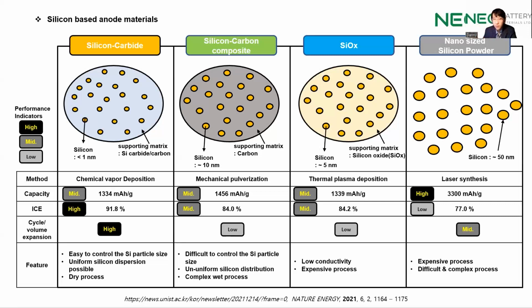So of course, these methods have their relative advantages, but in the industry today, battery cell manufacturers are finding difficulty implementing these solutions as they do not meet the required capacity, are expensive to meet profitability, and have particle sizes that are too small to handle. And you can see here that the silicon is about 5 nanometers in diameter, and smaller silicon particle means that there's more clumping problem of the silicon. And if the clumping problem cannot be solved, it cannot be effectively used in lithium-ion batteries today.